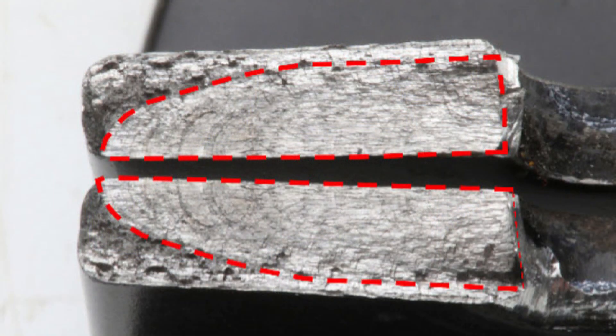Details from the examination of the failed right-front lift strut bracket: the bracket had 402.2 hours since installation, including the accident flight. A fatigue crack was found across the bottom end of the bracket, through the bolt hole and parallel to the bracket sides (figure 1). The initiation point of the crack was determined to be on the edge of the bolt hole. The fatigue region (figure 2) accounts for more than 60% of the cross-section area of the bracket.